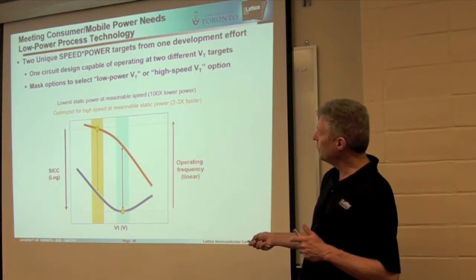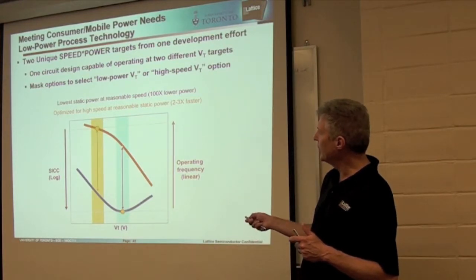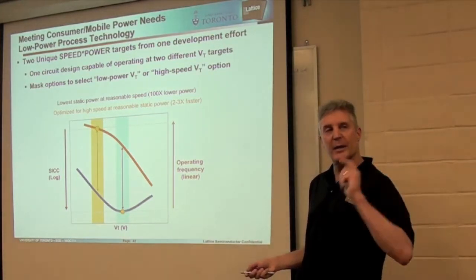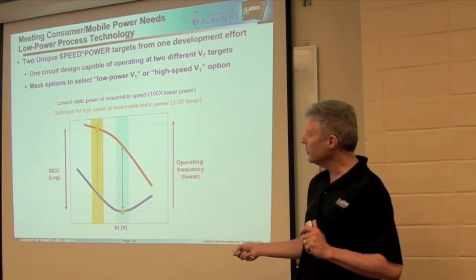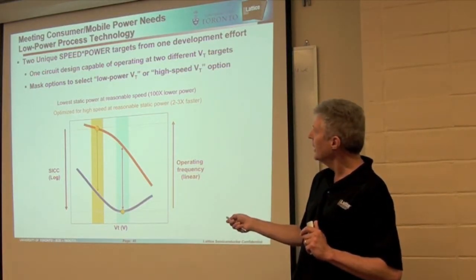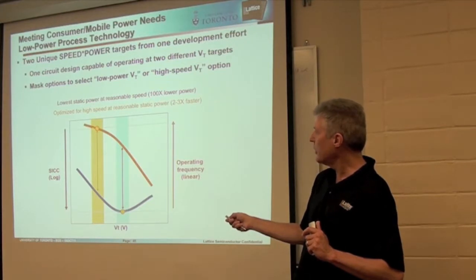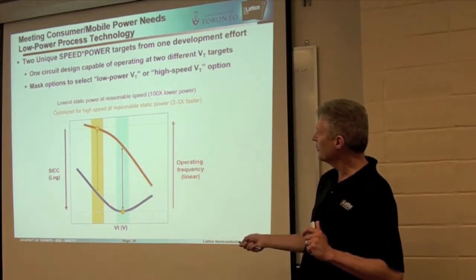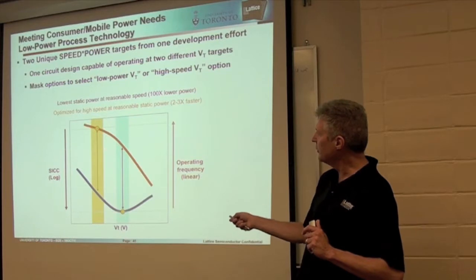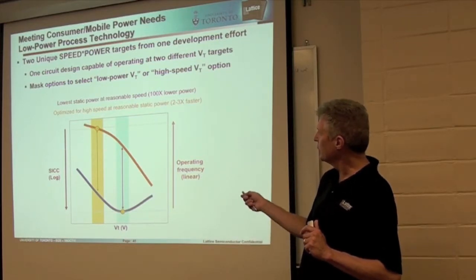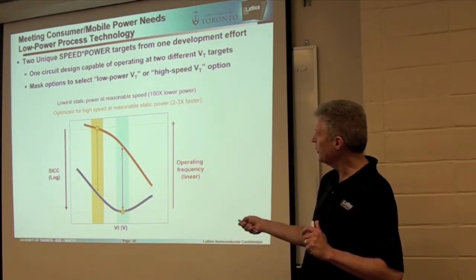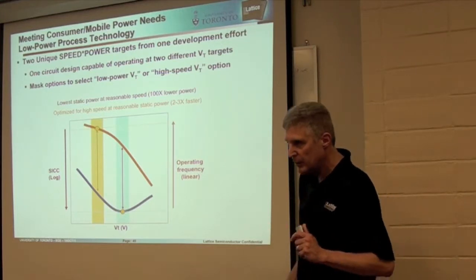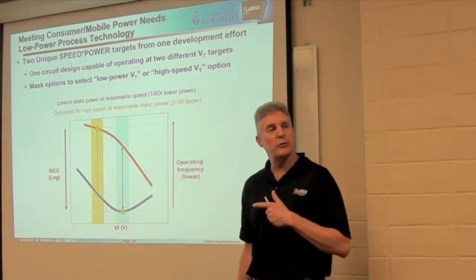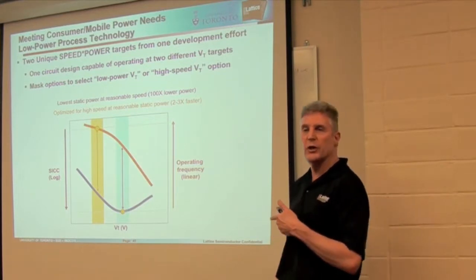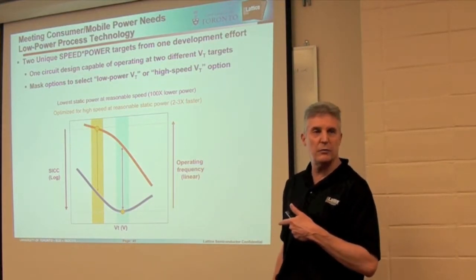So we built a product that you could implant with one threshold voltage and get the absolute lowest power at a reasonable speed, but implant it at a different, lower threshold voltage, and get a 2 to 3 times faster part, but it will cost you 100x power. Or put another way, if you want 100 times lower power, you can drop down here and pay only a small speed penalty to get that. So this is an interesting thing. It's the first time we've ever done anything like this. First time in the industry, I think, I've seen this done.